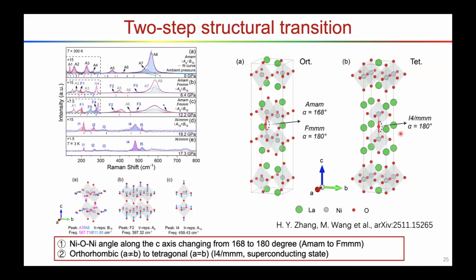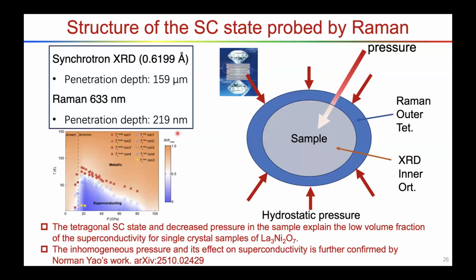But how do we understand the different results from different techniques? We thought about this question carefully. The structures were determined by synchrotron X-ray diffraction or Raman scattering, and they have different penetration depths. For synchrotron X-ray diffraction, the penetration depth is on the micrometer scale, but for Raman scattering, it's only 100 nanometers. That means when we measure in the diamond anvil cell with a big sample, the hydrostatic pressure will decrease inside the sample.